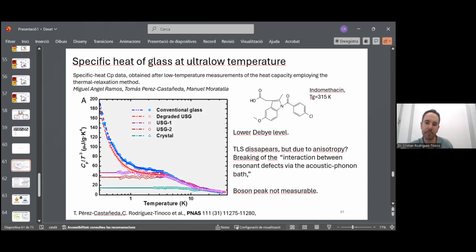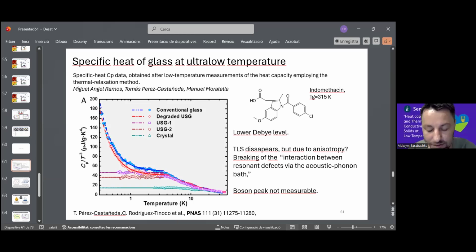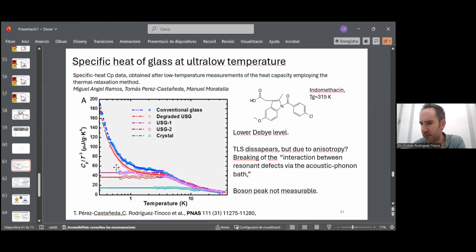Yes. So can you say the values of these temperatures of glass transition, and what is your opinion about correlations of the effect that you observed in the low temperature heat capacity? Can it in some way be correlated with this temperature of glass transition, or are they different subjects? Well, in this case, in indomethacin, the Tg of the ordinary glass is 315, as you see here. In the case of the ultrastable glass, if I remember well, it's 340, something like that. So like 30 degrees of difference.